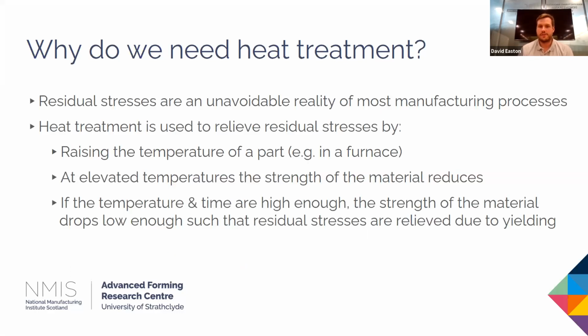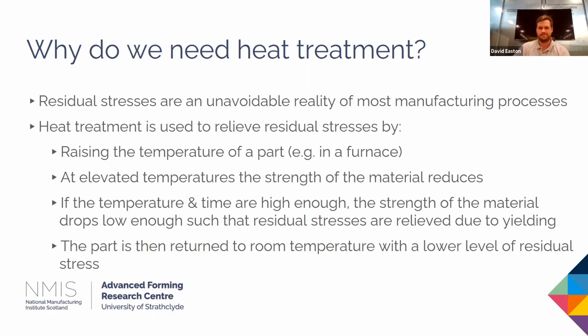So residual stresses are an unavoidable reality of most manufacturing processes. In order to relieve these, heat treatment is applied. So basically we raise the temperature of the part, for example in a furnace. As the temperature goes up, the strength of the material reduces. If the temperature goes high enough and we're at temperature for a high enough period of time, then the strength is low enough that the residual stresses are relieved, basically due to yielding. Then when you return the part to room temperature, you have a lower overall level of residual stresses.